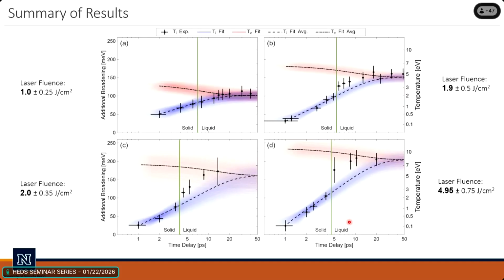One, the sample expands rapidly as soon as it melts, and we would confuse that for temperature in our diagnostic because we're measuring the velocity distribution. So that could be a massive expansion upon melt. The other is a negative latent heat type thing, where the heat capacity of the solid and the liquid are different, and that does genuinely create a jump in temperature upon melt in a superheated system, if you superheat far beyond melt. And the other one is that there genuinely is a jump in the electron-ion equilibration rate upon melt. Could be that too. So we're not able to distinguish between those in this particular experiment.